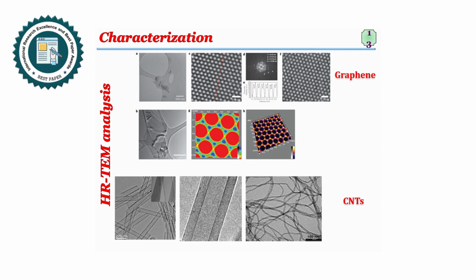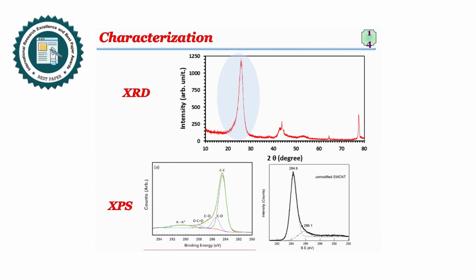Carbon materials can generally be characterized by HRTEM analysis for morphological analysis: the cylindrical tube-like structures of carbon nanotubes, the sheet-like structure of graphene, and the dot-like structure of carbon dots and graphene dots. They can also be characterized by XRD, with the characteristic 002 plane observed at a 2 theta value of 26.4.